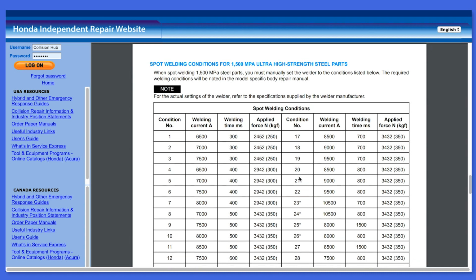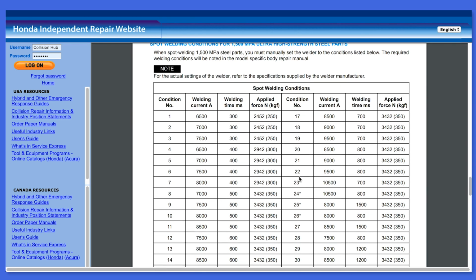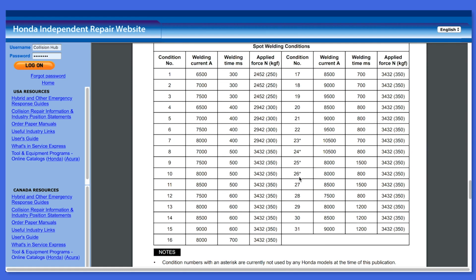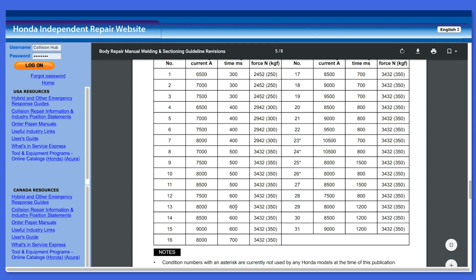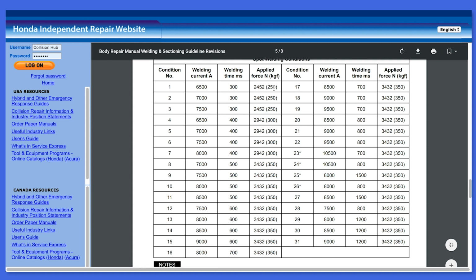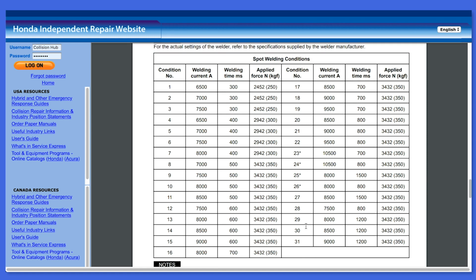And now they've got what they call weld conditions for 1500 MPa steel. You can see there are a number of different weld conditions, 16 of them to be exact. You'll see everything from 6,500 amps required all the way up to 9,000 amps required. They've got different times for different weld requirements, different electrode tip forces from 250 kilograms to 350 kilograms. I'm sorry, 31 weld conditions, not 16, my bad. So 31 different weld conditions, all the way up to 9,000 amps and 350 kilograms of force at the tips. Where you find this, we'll dive into a little deeper momentarily, but it's in each procedure. They're going to give you a chart, and they're going to call out specific welds and exactly where they want you to use these different weld settings.